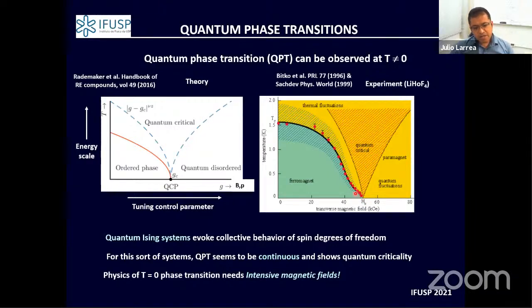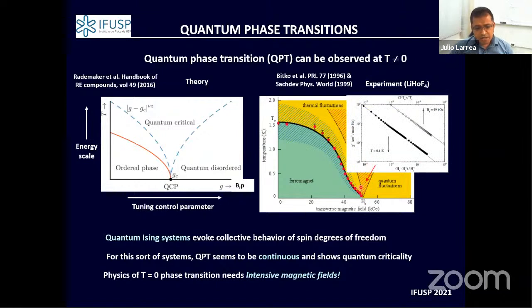The quantum critical behavior appears even at finite temperature. In principle, if you try to measure a magnetic susceptibility in the vicinity of this quantum critical point, you will see the quantum critical behavior showing as a power law over a large range of temperature, different from the other parts of the phase diagram.